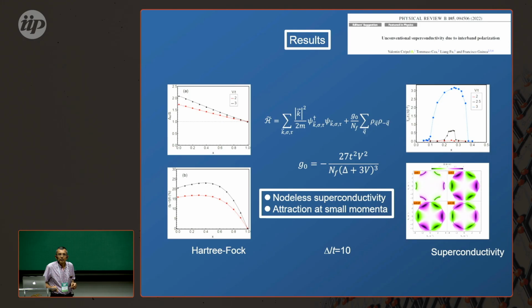No, not necessarily. You can have an order parameter which breaks time reversal. What we did is we studied the problem in reciprocal space, in momentum space, and we linearized the gap equation, and we solved the BCS gap equation for this model in reciprocal space. We obtain the gap as a function of momentum.